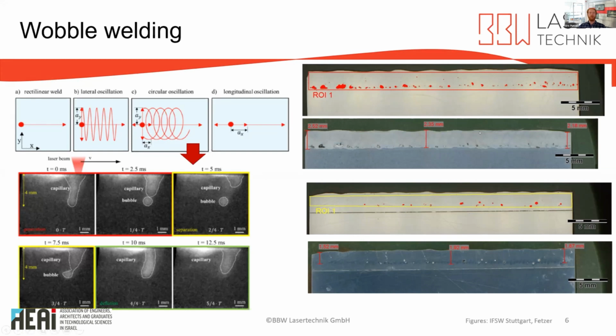On the top, we have a cross section for a weld seam without the wobbling technology. We have here a relative porosity of around 2.5%. On the bottom, you see another cross section for a weld seam with exactly the same parameters, but with additional wobble technology. So here you can see the welding depth is a little bit lower, but also the porosity is significantly decreased from 2.5% down to 0.6%.